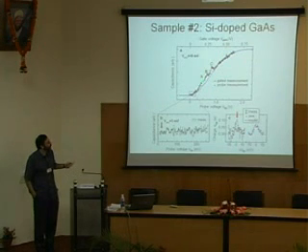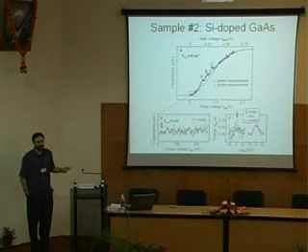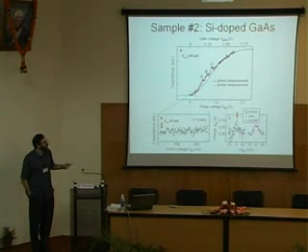On top of the background, though, we see 3 bumps, A, B, and C. And these were quite reproducible. Wherever we went, we saw these 3 big bumps, A, B, and C. The single electrons are way down here. You can't even see them on this plot. It turns out these 3 peaks are something like 15 or 20 electrons all clustered together, giving you this broader structure.